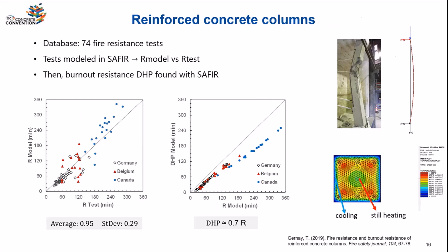And what we call DHP is the shortest duration of heating phase that results in a failure. So it's basically the threshold of thermal exposure that the column has been subjected to so much thermal exposure that it will fail eventually. And what we found, so again, because of this delayed heat transfer, when you enter into the cooling phase, you have the core of the section that continues heating, even though the perimeter starts cooling. And so what we found is that there is approximately a linear relationship between the burnout resistance and the fire resistance. In other words, if you have a concrete column which has a 90 minutes fire resistance, it would fail eventually if you expose it for the heating phase for more than 63 minutes or more.